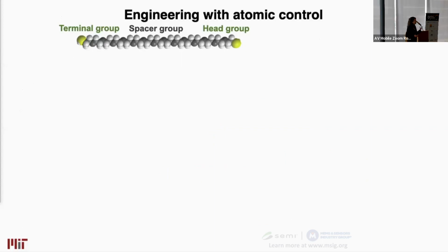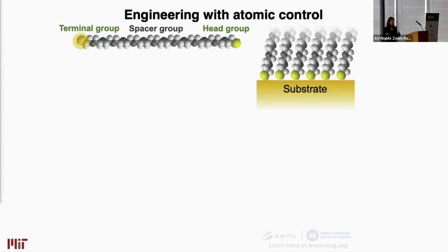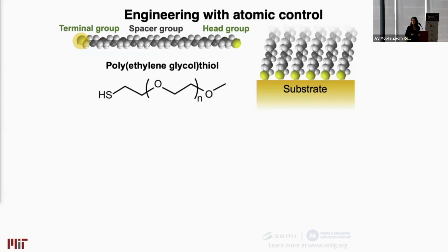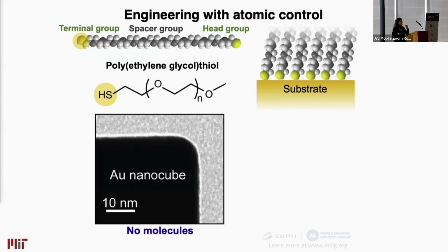So as I said, we have atomic precision in designing these molecules. One advantage is we can make these molecules with functional groups that we desire, which allows them to spontaneously assemble onto a desired surface, for example, the contacts of your device. So here I'm showing you a molecule of polyethylene glycol thiol, where the sulfur-hydrogen, or thiol, group allows the molecule to selectively assemble onto surfaces like gold.